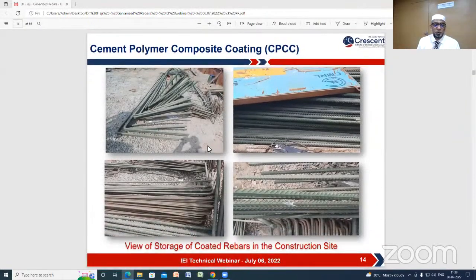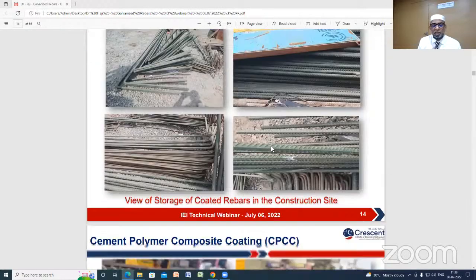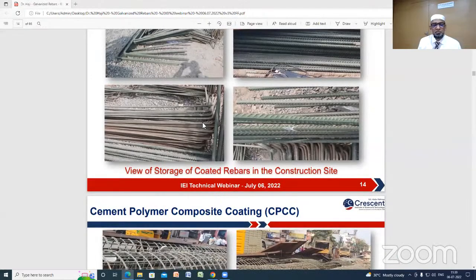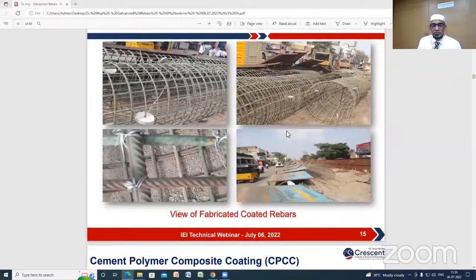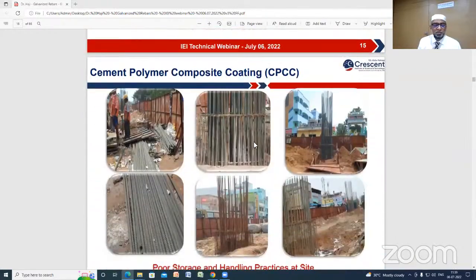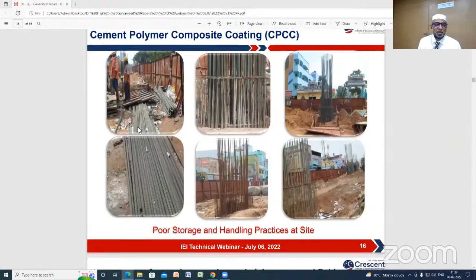These are some photos taken at site where cement polymer composite coating was used; again, poor construction practice leads to corrosion of the coated rebar itself before concreting. This is again a picture of very poor construction practice; these rebars have to be stored over wooden planks, but the procedure is not followed.